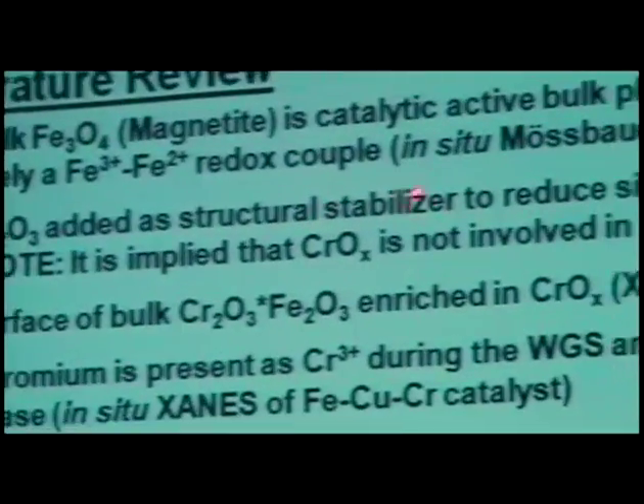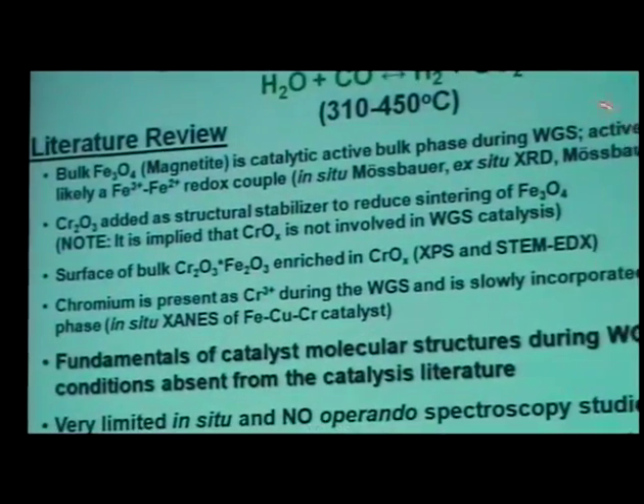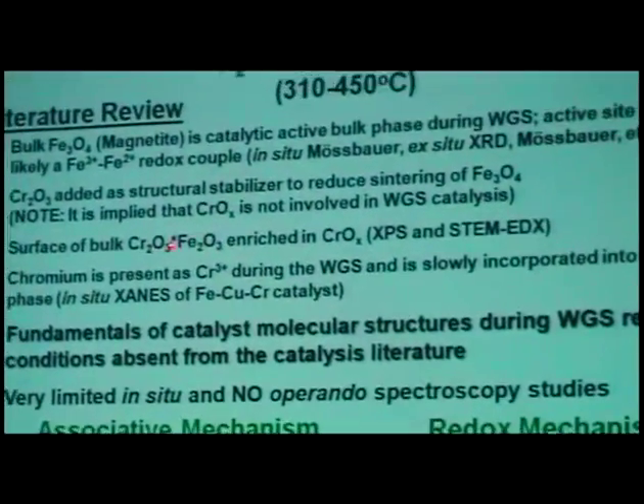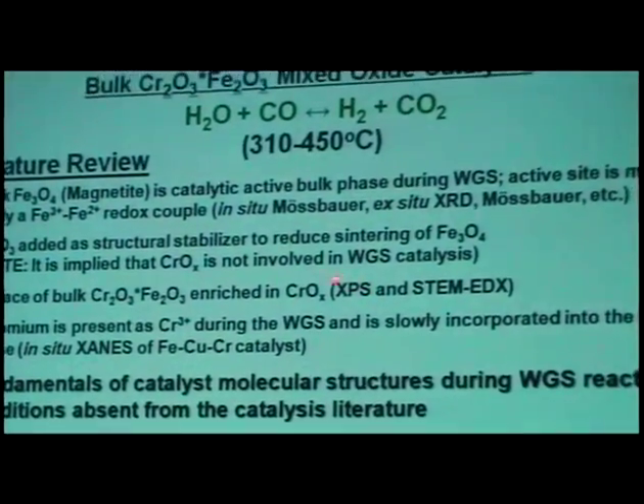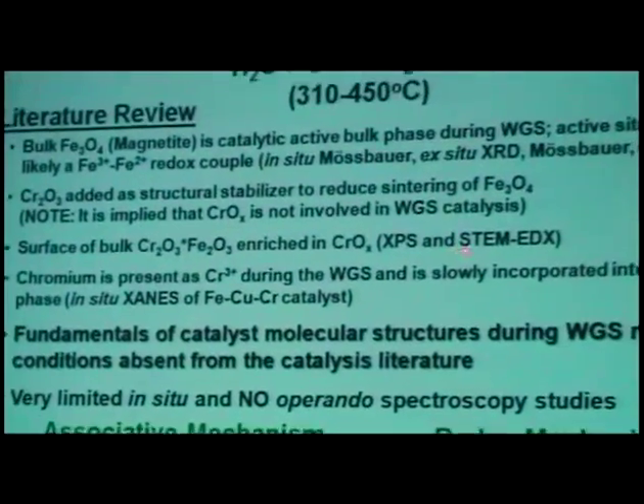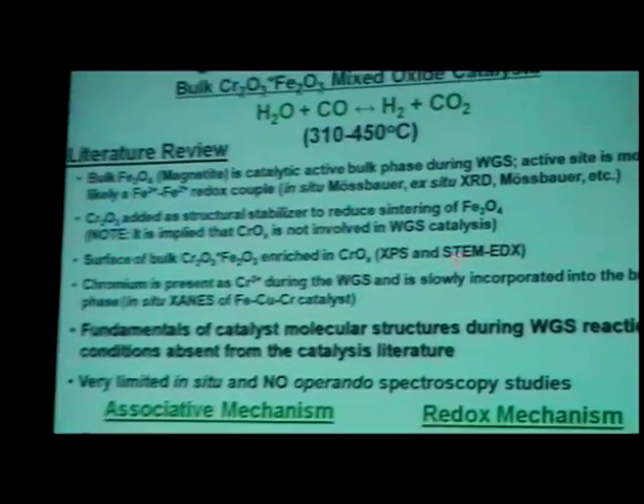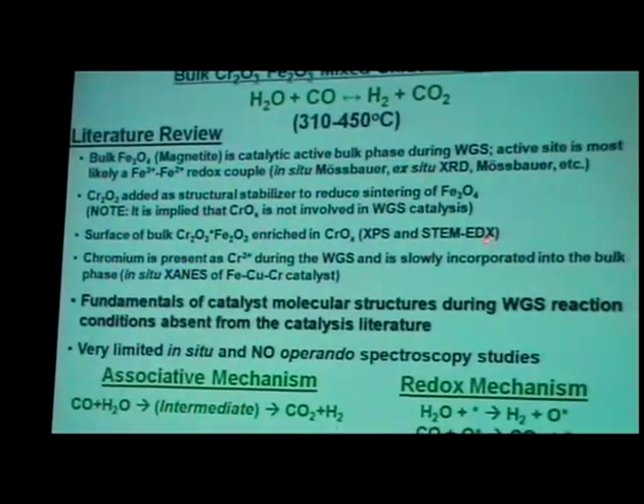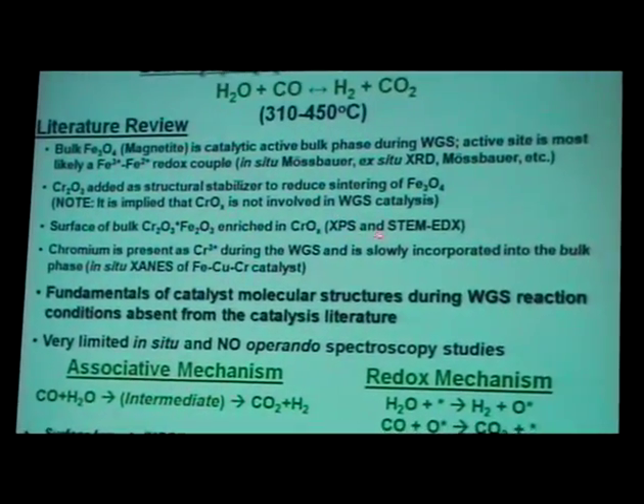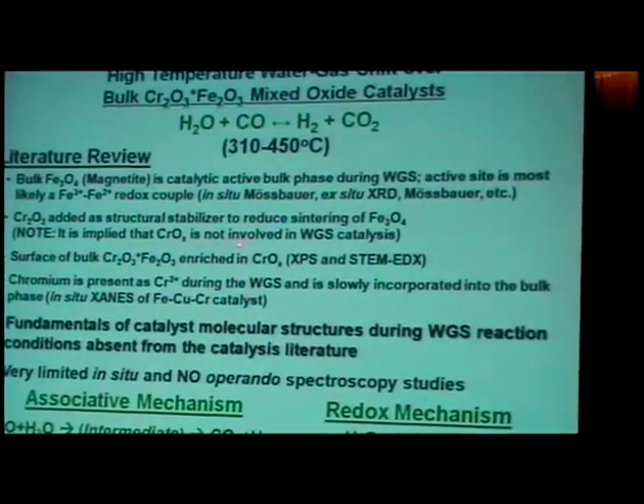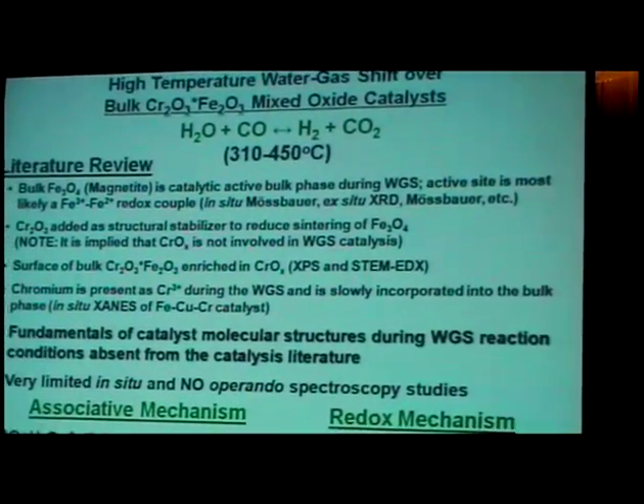What is the role of chromium? Well, the literature claims that the role of chromium oxide is a stabilizer to reduce sintering of iron oxide. The iron oxide will sinter. XPS studies and high resolution scanning transmission electron microscopy studies have indicated that there appears to be excess chromium in the outer surface of the catalyst. But beyond that, these were catalysts pulled out of the reactor. They're not looking at it during the reaction.